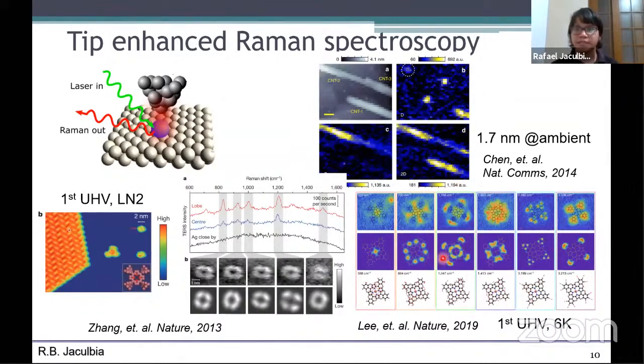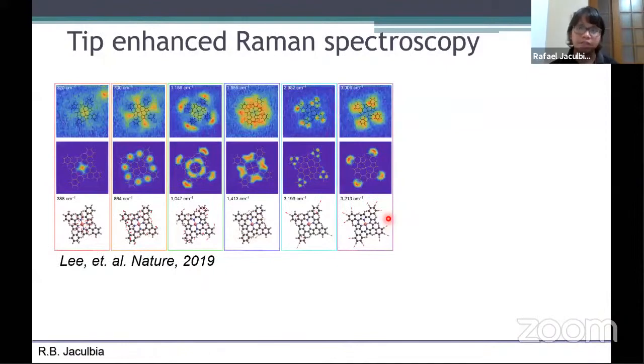So this result was very groundbreaking last year, and it finally experimentally verified the theoretical predictions that were made a very long time ago. However, in this work, in order to achieve this great result, they have about 2 angstrom of spatial resolution. So as you can see, you can separate or individually identify features within one small molecule. Note that this molecule is about 2 nanometer, I think. So it's very small.